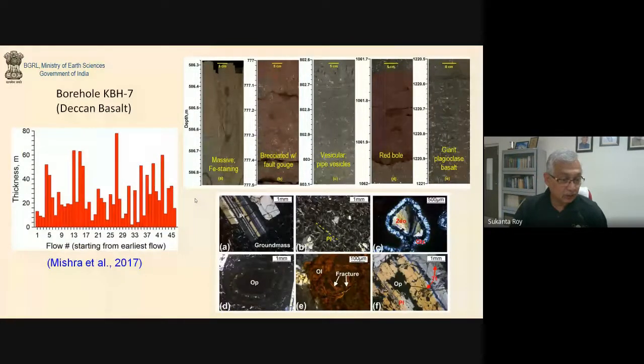Shown here on the left hand panel is a plot showing the distribution of the thicknesses of the different flows, and on the right you can see the different features that we saw in the basalt core. Iron staining around the fractures showed that water really percolates down deep, up to at least 1500 meters depth. Then brecciated fault gouge, and evidence for pipe vesicles, particularly in the compound flows. We have these pipe vesicles, red bole beds, and giant plagioclase basalt. These were mostly found at the base of the trap sequence.